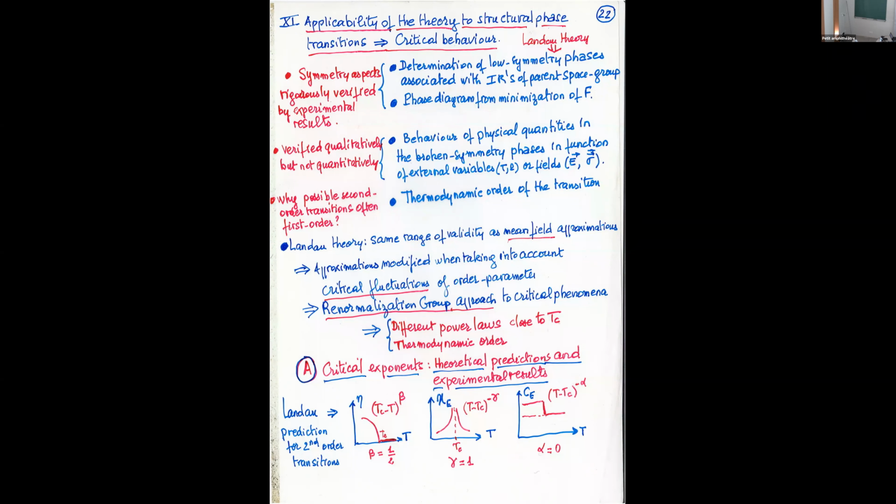I can give you an example. If you find more domains in the phase which appears in your phase diagram, which are not predicted using the parent phase that appears first, then of course you can say perhaps there is a latent parent phase which is not here in the phase diagram, but that should be taken as the parent phase for the system.